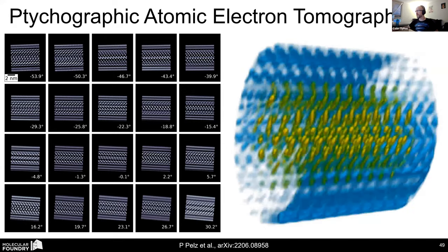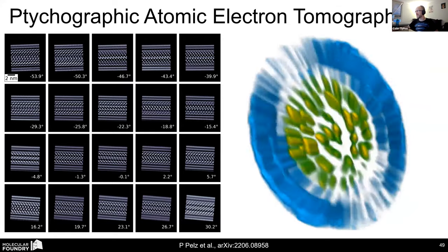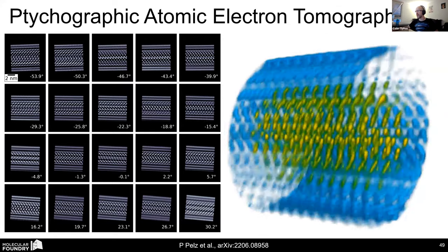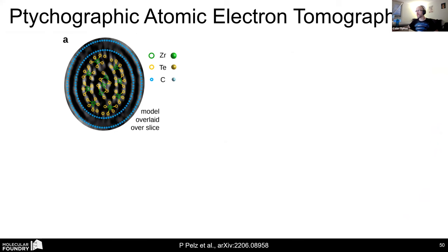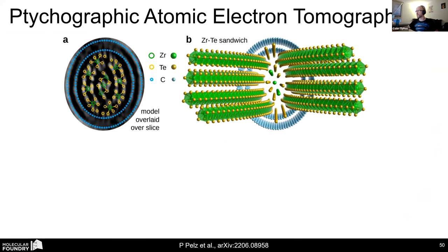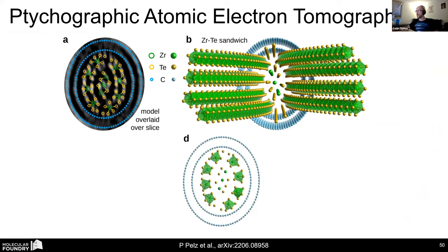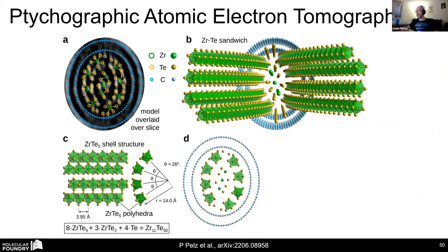Then we fit the carbon nanotube and traced out all the zirconium and tellurium positions inside this volume here, and discovered quite a rich, very interesting internal nanowire structure. Here's just a quick sketch pulling apart the different layers. I just wanted to mention the overall structure. It has this known zirconium telluride 5 structure, but instead of forming a continuous crystal, you have on each side four individual units here that are rotated about 25 or 26 degrees with respect to each other, and they sort of form a shell of the nanowire.